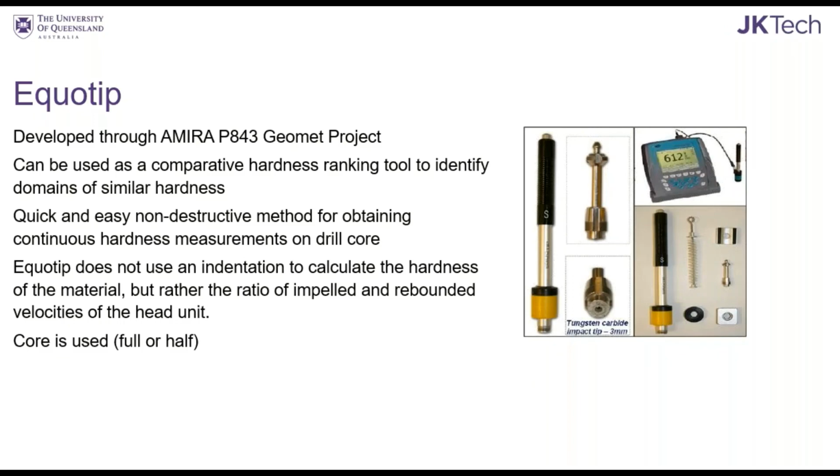for continuous measurement of, I guess you'd call it, surface hardness. It's a pen type device which you go along down your core to get a surface hardness measurement, also called leeb hardness. This device came from a different industry to test the hardness of various materials. So it was decided to test it down core, and it does seem to work quite well.